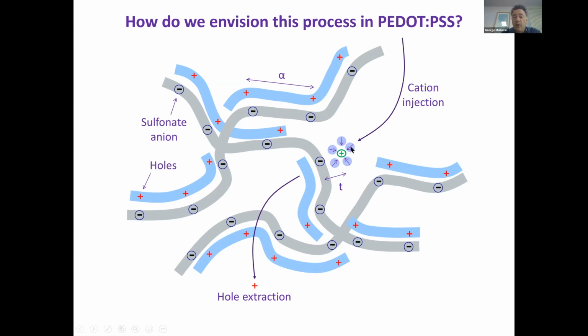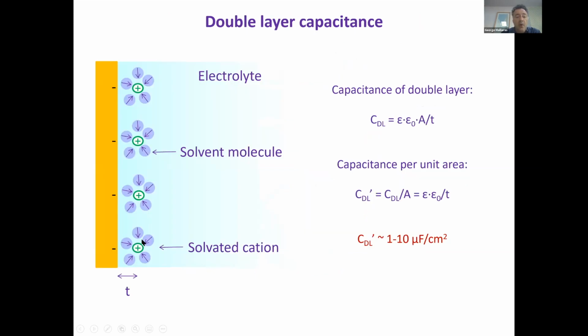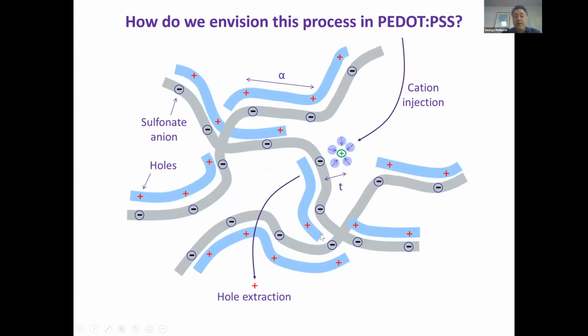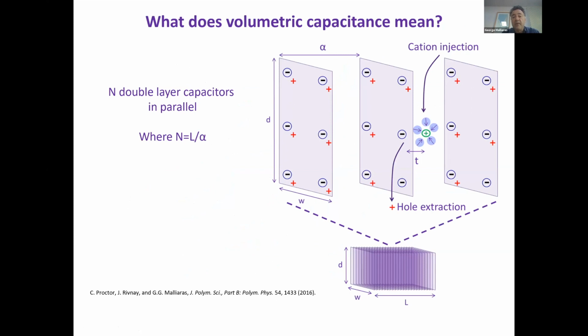So what you do is you form a little capacitor here in a similar vein as the Helmholtz capacitor shown here. And these are distributed throughout the volume. So what you need to know is what would be the distance between these ions, this and the next one, which you can infer from the doping density of PEDOT:PSS. And then you can come up with a very simple toy model where you slice the volume into thin slices and account for how many capacitors you can have per unit volume. And this is a back of the envelope calculation.